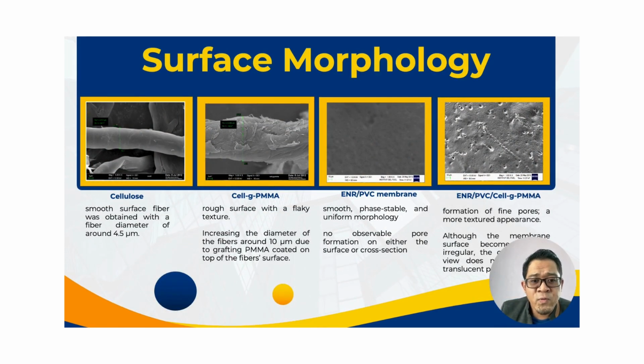Then we go through the surface morphology. First, we see the cellulose shows a smooth surface fiber with a fiber diameter of around 4.5 micrometer. The cellulose grafted PMMA shows a rough surface with a flaky texture, increasing the diameter of the fiber to around 10 micrometer due to PMMA grafted and coated on top of the fiber surface.